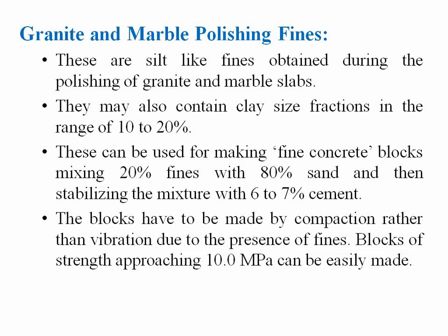So you can use this granite and marble polishing fine to produce fine concrete blocks by mixing 20% fines with 80% sand and then stabilizing the mixture with 6 to 7% cement.